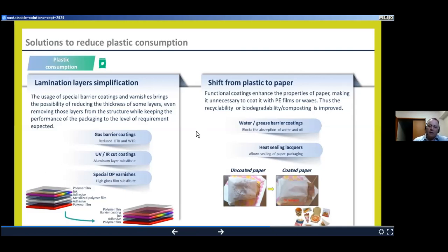And when we speak about paper, because some of the brand owners are looking for moving from plastic packaging into paper packaging, we need to protect the paper packaging from the food which is contained inside. In this case, it can be water or oily food. Normally this kind of paper or cardboard is laminated either with wax or with polyolefin film. So in order to make this 100% recyclable and get rid of the mix of paper and film, we are offering water and grease barrier coatings and also heat sealing lacquers in order to be able to heat seal this kind of packaging without using the typical polyethylene film.